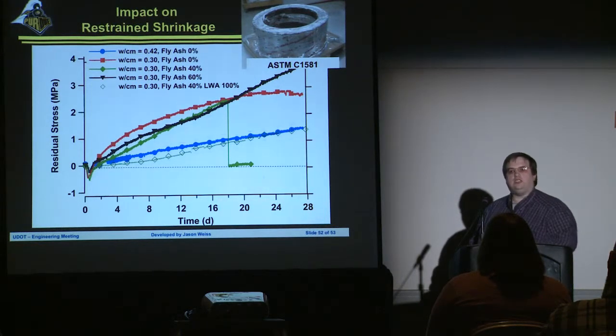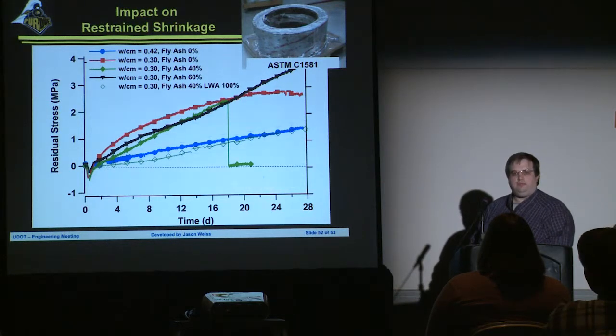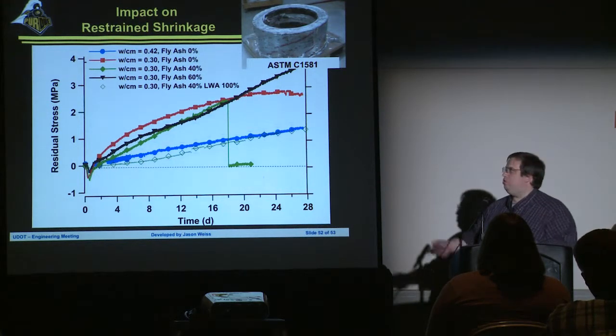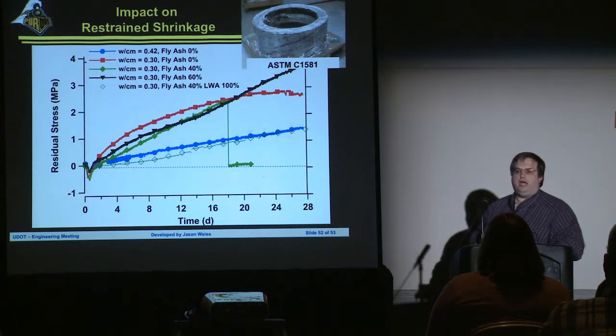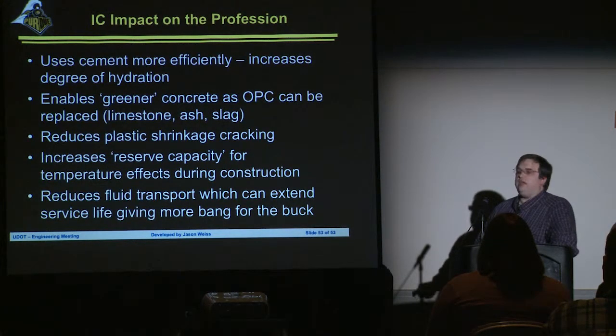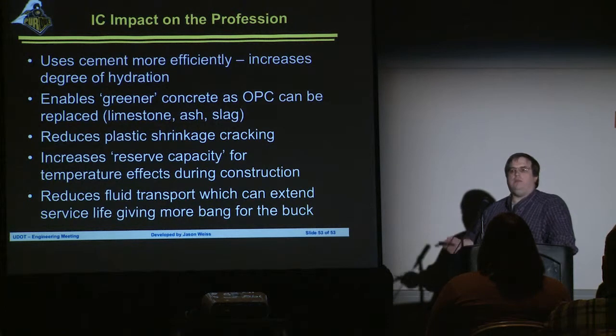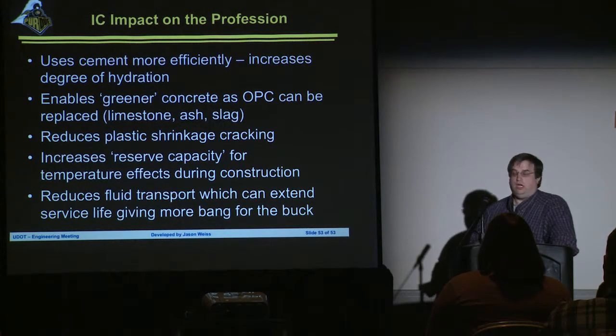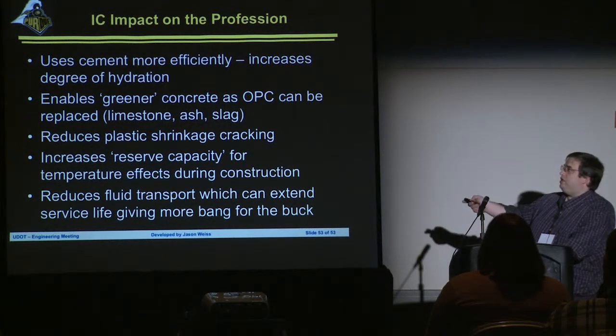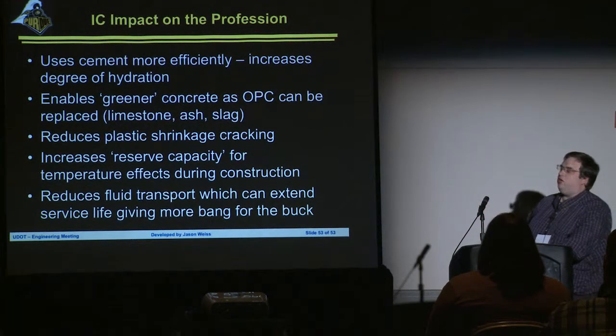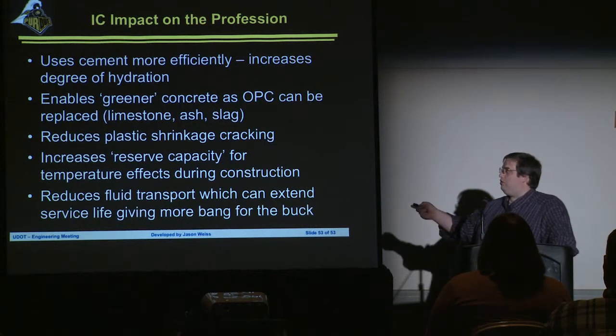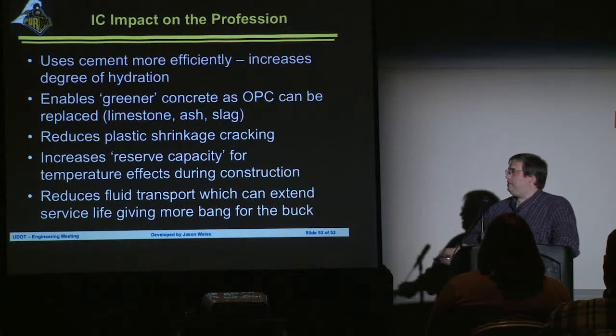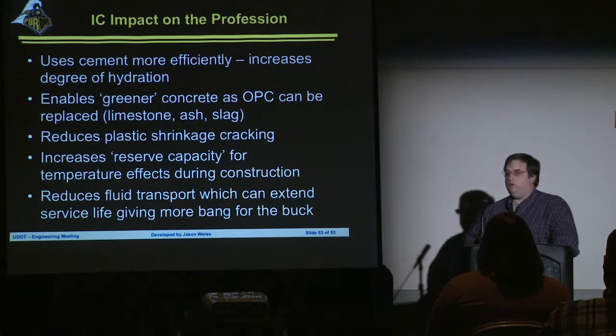So really what we're looking at in sustainability here is we're saying we can replace 60% of the cement, get rid of 60% of the CO2 using fly ash combined with internal curing. In addition to that, we get rapid chloride permeability numbers that are about 10 times lower than what we see in the conventional mix design. So we think that there's some huge benefits here because we're going to enable greener concretes to be used, gives us reserve capacity, and really reduces fluid transport. And with that, I will see if there are any questions.